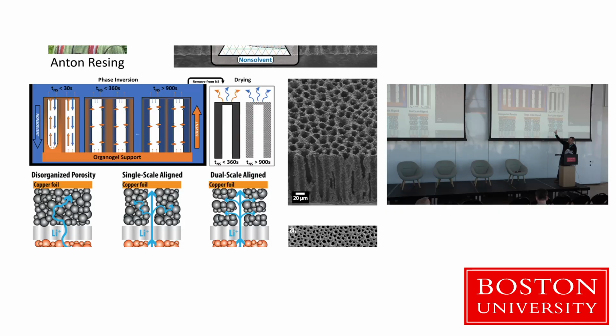It happens in that step where these channels form. That happens within 10 to 20 seconds. What happens afterwards is shown on the right in the schematic. More and more solvent gets drained out of these polymer particle walls. There's a lot of that trapped in there. It's like a gel. And the longer we leave it in there, the more solvent we remove by extraction. And this can take hours.